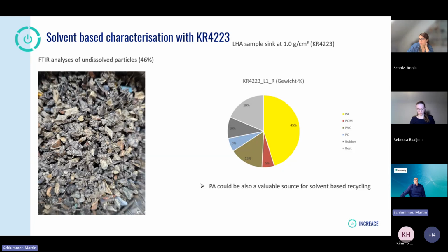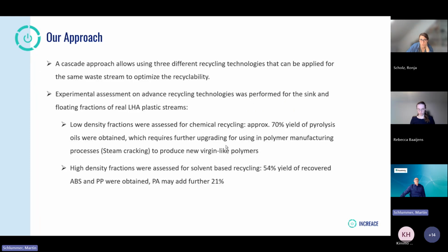If you look into the leftovers in the solvent-based recycling so far, we see a large share of polyamide. This suggests that another dissolution step for polyamide may add another roughly 20%. So for this approach, very briefly, the impression is that this cascade allows us to combine all three technologies and to increase the overall yield. The experimental assessment so far showed that we could make use of the sink and the floating fractions.